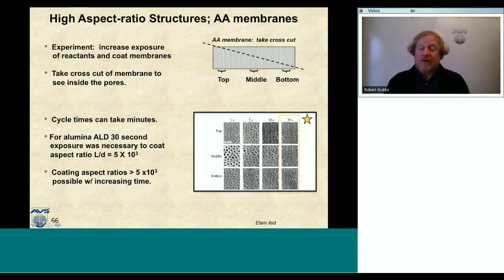So it looks like you can coat these anodic alumina structures conformally, you just have to wait 30 seconds for each pulse and for each purge time. So now you've taken cycle times that have been maybe 12 seconds, and cycle times are now on the order of minutes. But the good news is that you can actually coat these things. And so coating aspect ratios of maybe greater than 10 to the 3, 1,000 to 1, is possible, but at the cost of spending more time allowing your precursors to molecularly flow down the trench or down the pore, and then for your reactant or product molecules to come back out.